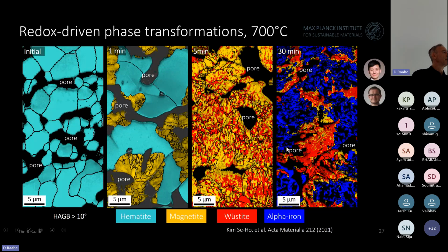Sometimes you see in papers also very high temperatures in direct reduction, which I think is in part a bit questionable because you don't want to arrive in gamma iron because then the diffusion coefficients will be very low. So one must, for a reactor scale, where we also do collaborations with people who do the complete gas dynamics simulations for complete reactors, keep in mind the rather complex temperature distribution inside of these furnaces. You also learn from this diagram a rather heterogeneous progress of the reduction. That means we still find patches of magnetite and wüstite. So there's not always just a very linear progress of these phase transformations.